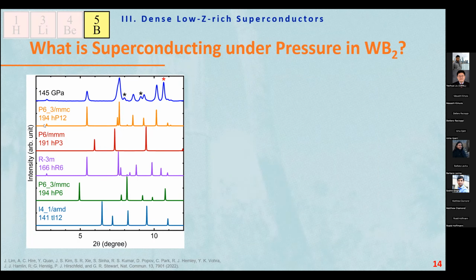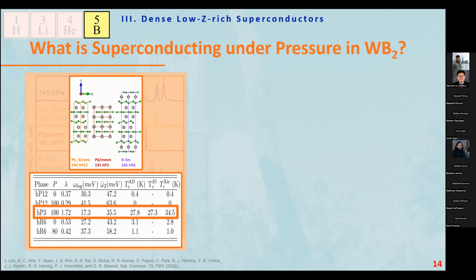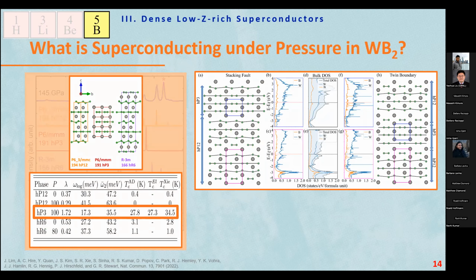This is the MgB2-like structure peaks calculated, and we compare with this, and we didn't find any. But this is the ambient pressure structure, hP12, and this fits well up to 145 GPa. So we didn't have any MgB2-like structure in the bulk form. So that gives you our idea about the planar defects.